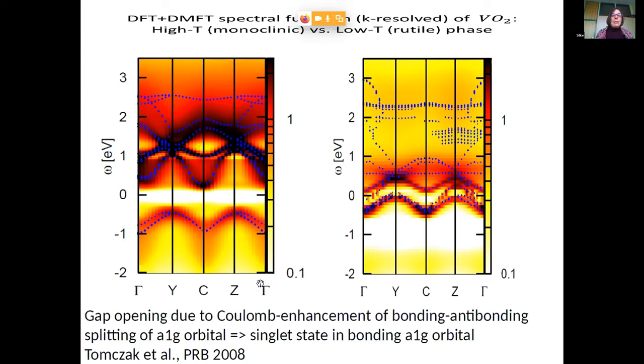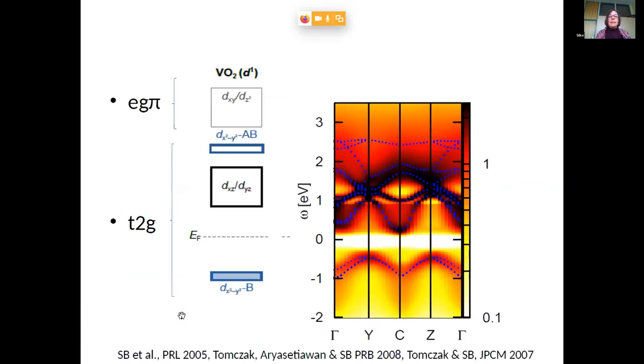In the insulating phase, at first sight surprisingly, but if you think about it a bit further, actually not so surprisingly, things are much better defined. So here, the maxima of the spectral function follow something which can, to a very good approximation, be described by a band picture. And actually, the first trivial observation is that you open up a gap at the Fermi level. That means you have now, indeed, the spectral function corresponding to an insulating state. You can further analyze how this comes about. In fact, the states down here do indeed correspond, as postulated by Goodenough, to a bonding A1g orbital character. And that means that we can analyze this spectral function in terms of bonding A1g, anti-bonding A1g, which shows up here, and the stuff in the middle is actually the EG pi states.